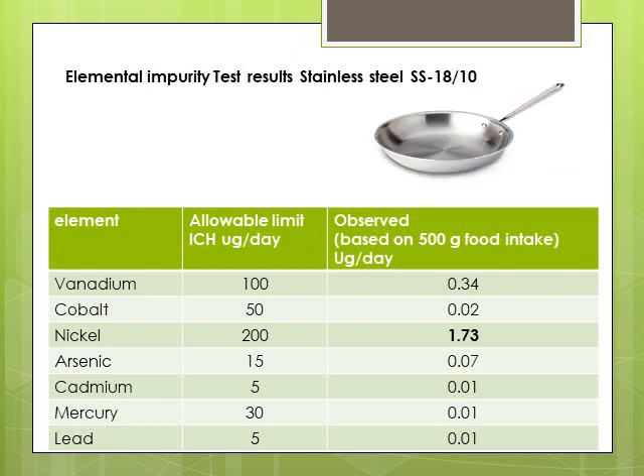The next one is a stainless steel SS1810. Now I don't want to read the elements and allowables. I just jump to the observed ones. Vanadium, again, 0.34. We don't see much. Cobalt, we don't see much, 0.02. Nickel, we see 1.73. Although it is less than allowable 200, it is rather more significant, or significantly higher than the previous cookware made of this black aluminum.